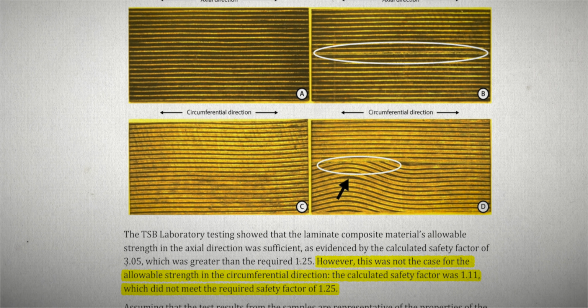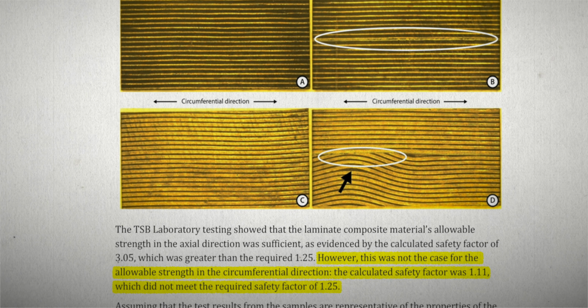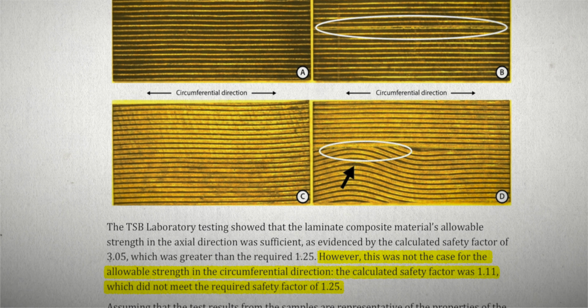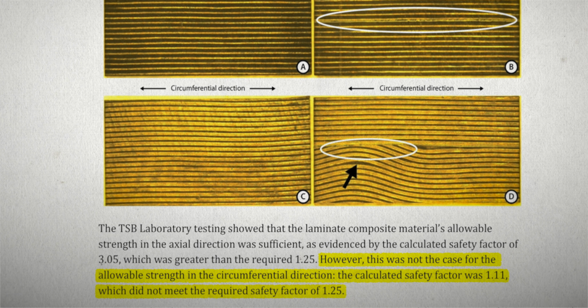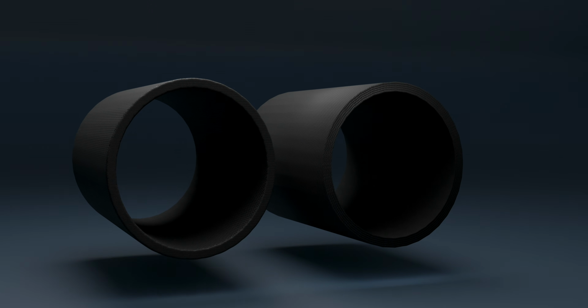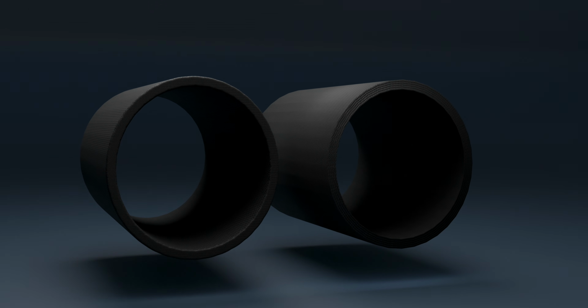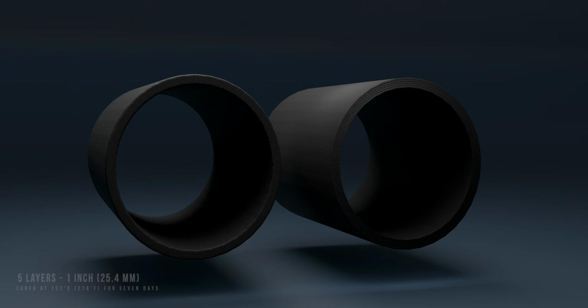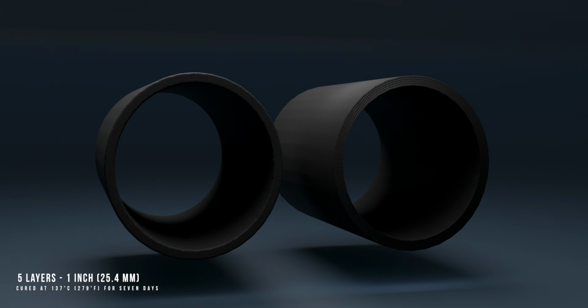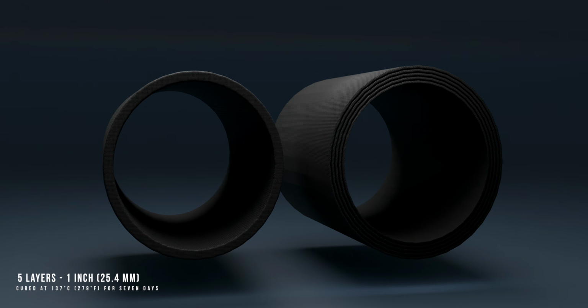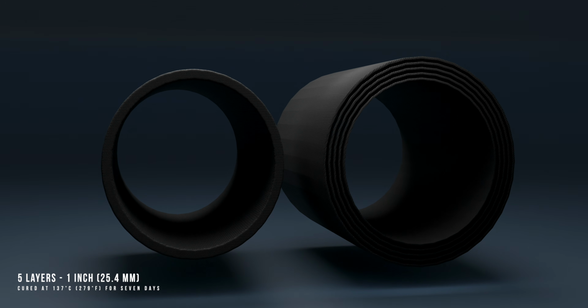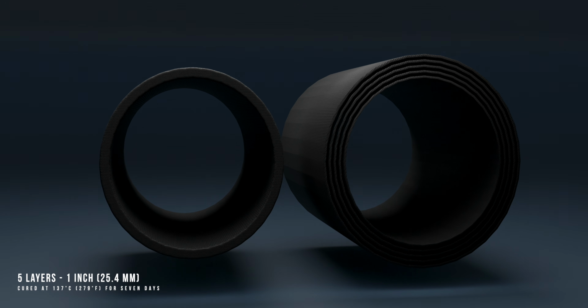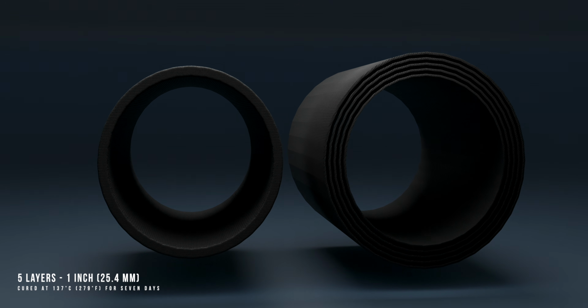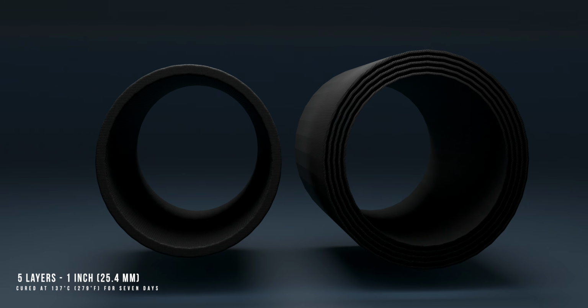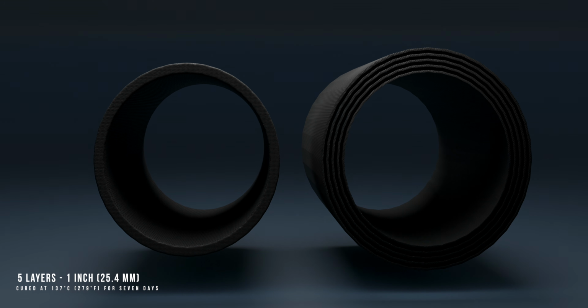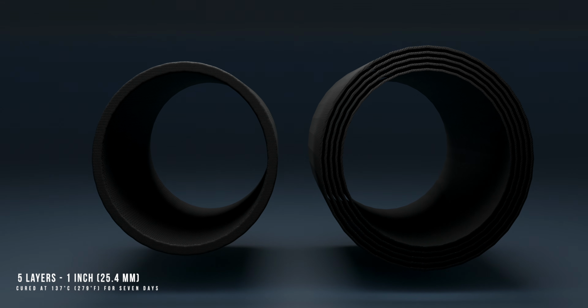The investigation also found that many of Titan's problems originated during manufacturing. Instead of being fabricated as a single 5-inch thick laminate, the pressure hull was built in 5 separate 1-inch sections, each cured before the next was added. This meant the innermost layer, the one subjected to the greatest stresses during every dive, underwent 5 separate curing cycles, repeatedly exposing it to heat that may have degraded its long-term mechanical properties.